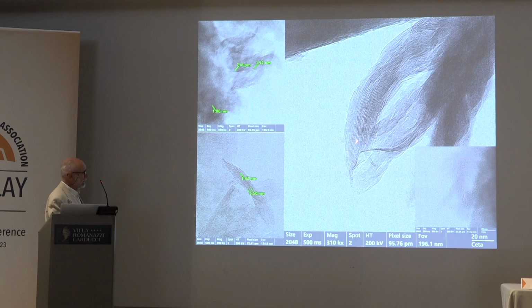So the common spacing is between 10 angstrom and 14, 15 angstrom. You see this, the lateral continuity is very, very limited. And also the stacking. So we have the stacking 2, 3. In the best case, we have 5.